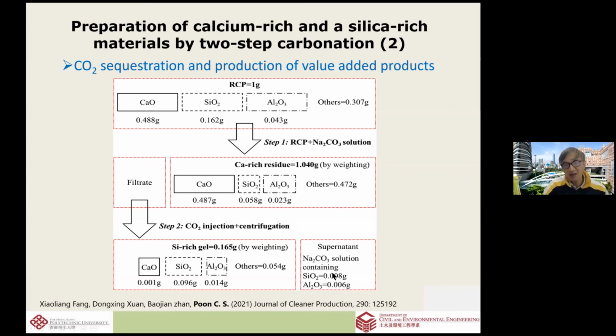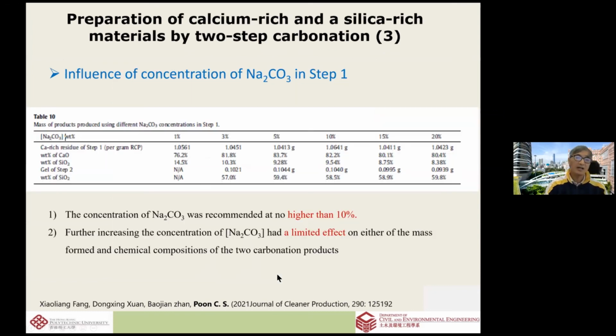And then the filtrate, which is very interesting, is mostly returned. Because we add sodium carbonate solution as the essential start-off chemical, but after all this processing, we come back with the sodium carbonate solution, so it can actually be recycled. Also, there is no wastage. So we are trying to understand the influence of the concentration of sodium carbonate solution on this carbonation step. After the experiment, the paper, if you're interested, is already published, but this process was patented before the paper was published.